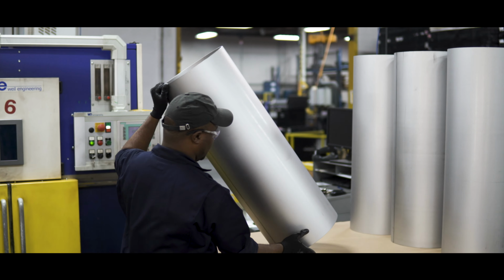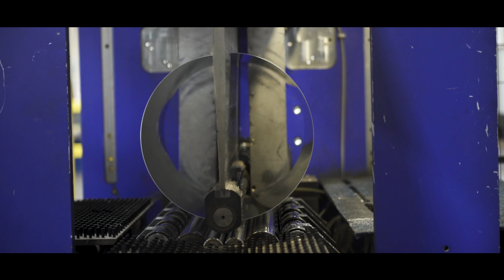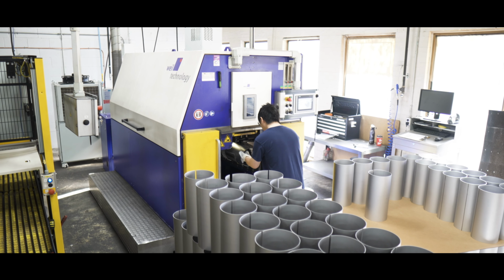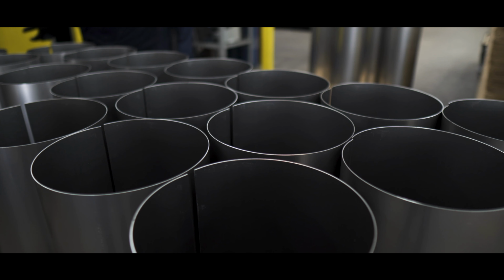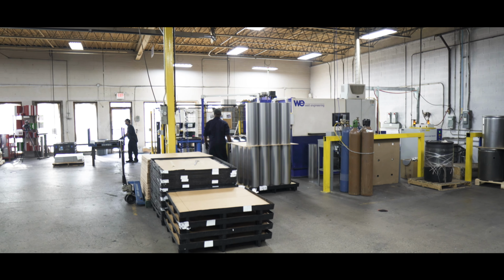The Weil Technology, putting the TIG on there, allowed us to make a very round part with a repeatable weld where the spin can go across it without a lot of ripping. We were able to spin deeper. There was a much smaller heat affected zone, and our customer was far happier with the product we got after we started to TIG weld with the Weil equipment.